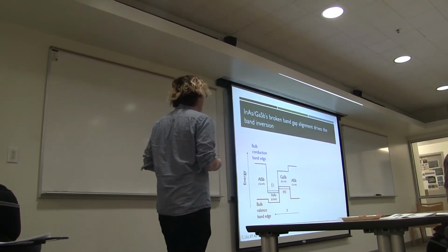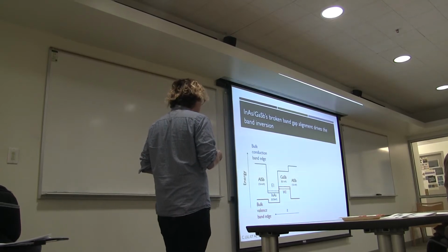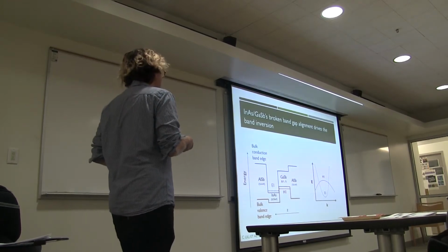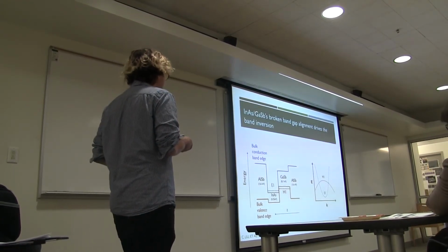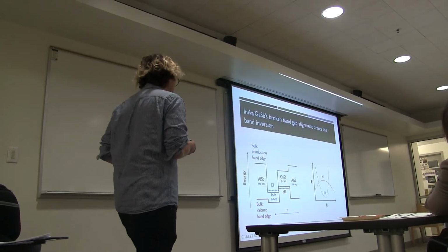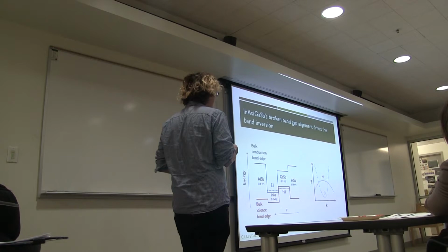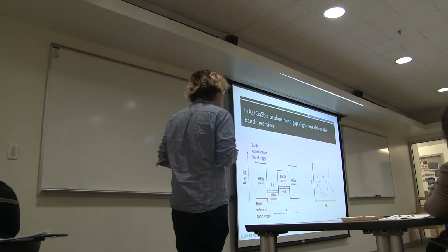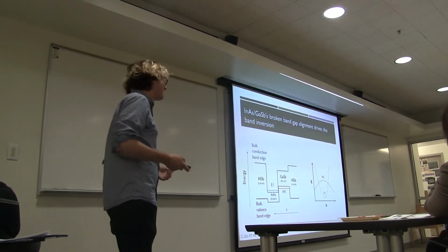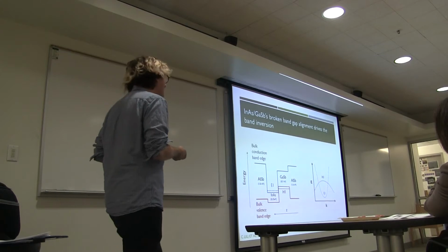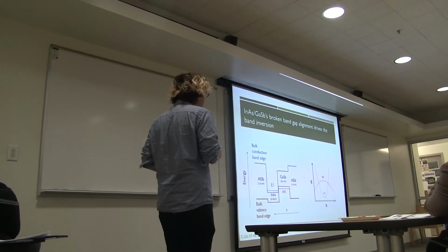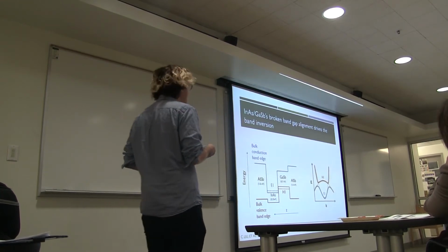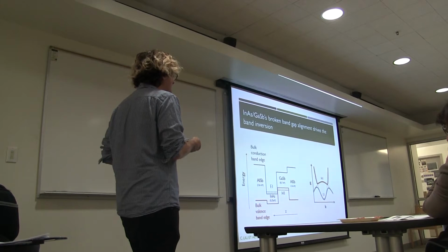The other interesting thing about indium arsenide and gallium antimonide is that the electrons and the holes live in two separate layers. And so if we take a given thickness of indium arsenide and gallium antimonide and calculate what the electronic structure should look like, indicated by these dashed lines, we find that we do get the band inversion we want. The H1 band, the gallium antimonide valence band, lies above the indium arsenide conduction band. But we don't have an insulator anymore. There are states everywhere, so there's no gap. It turns out that we have to include tunneling between electrons and holes in order to open this gap. And so now we have this weird looking energy gap, but there should be quantum spin Hall edge states that live in this gap.